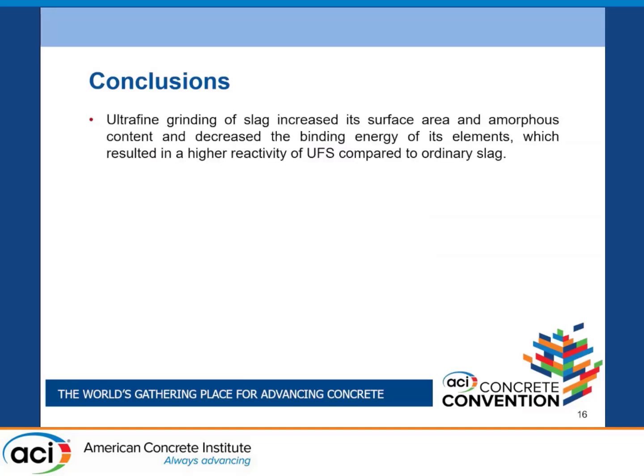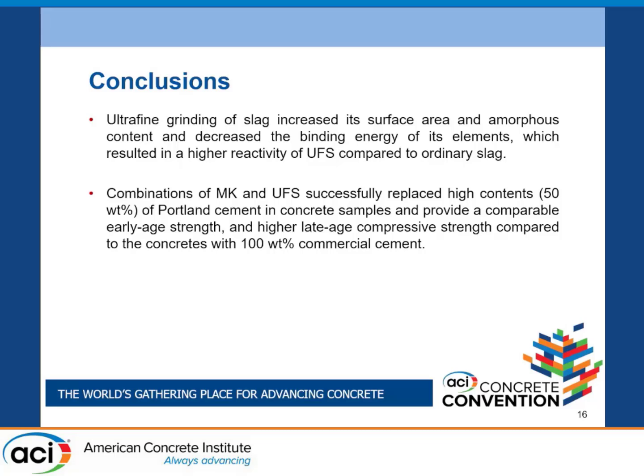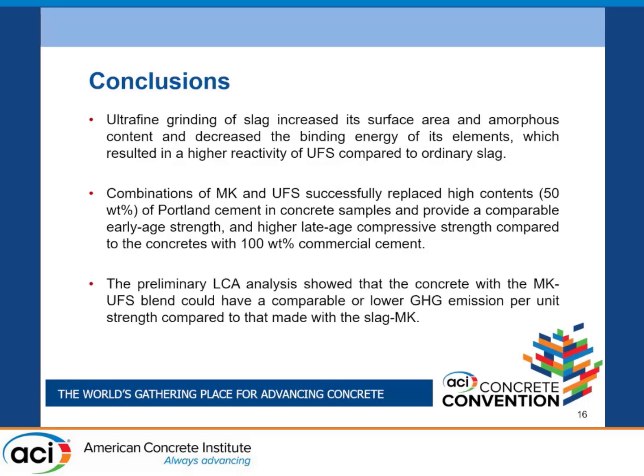For the conclusion, we saw that ultrafine grinding of slag increased its surface area, decreased particle sizes, increased amorphous content, and decreased the binding energy of elements, which resulted in a higher reactivity compared to ordinary slag. In our concrete, we replaced 50% of Portland cement. We obtained comparable early age strengths and higher late age strengths compared to the sample with 100% commercial cement. And our LCA results show that the concrete with metakaolin and UFS could have a comparable or even lower GHG emission per unit strength compared to that made with slag and metakaolin.